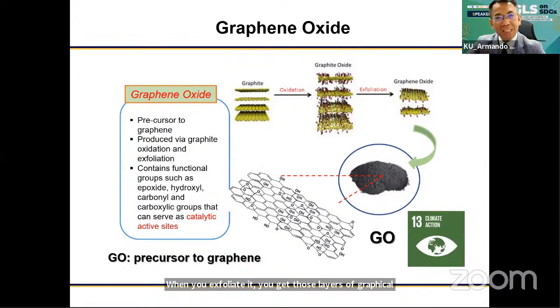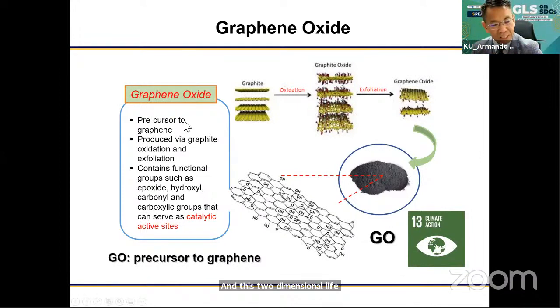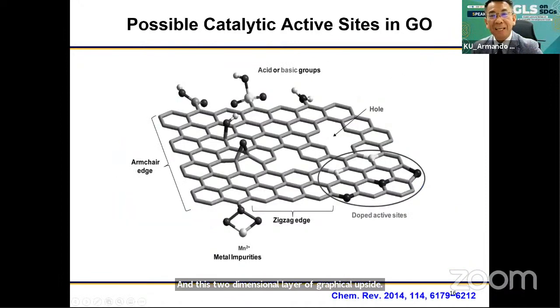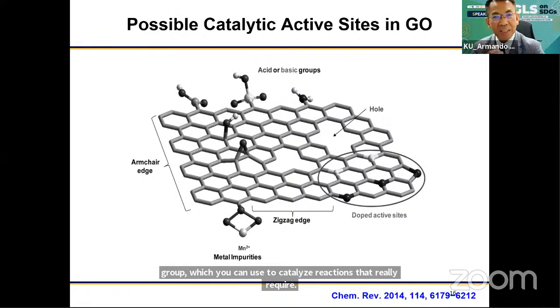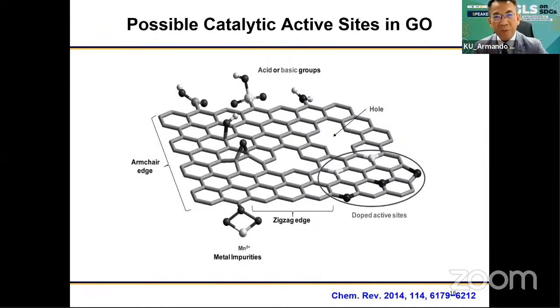And this two-dimensional layer of graphene oxide has many chemical and physical properties that we can utilize in order to catalyze our reactions. These are some of the possible catalytic active sites on the surface of graphene oxide. We have the basic group, which you can use to catalyze reactions that will require base catalysts. Acidic part, again, you can use in order to catalyze reactions that will require acidic catalysts, and so on. A lot of possibilities for these very versatile catalysts, graphene oxide from graphite.